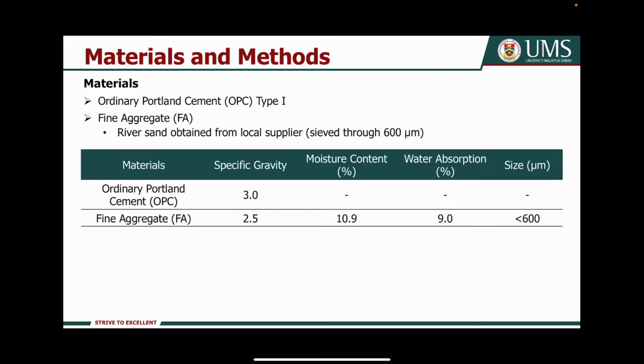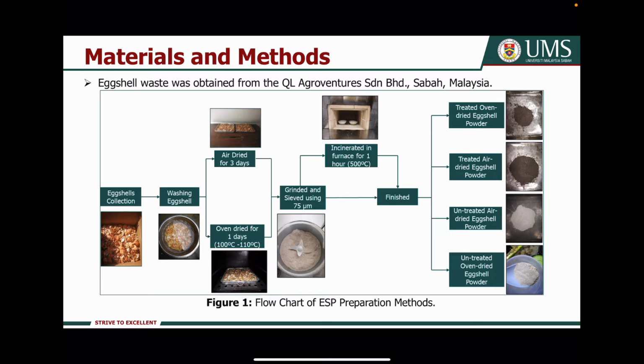This research used type 1 ordinary Portland cement and fine aggregate, which is river sand, obtained from a local supplier. It is sieved through 600 micrometer. The eggshell waste used in this research is obtained from QL Agroventure Sdn Bhd. It is then washed to remove the extra debris and then dried by using the air-dried method or oven-dried method. The next day, it is ground and sieved using 75 micrometer and then incinerated in the furnace for 1 hour. This preparation method will produce treated oven-dried, treated air-dried, untreated air-dried, and untreated oven-dried eggshell powder.